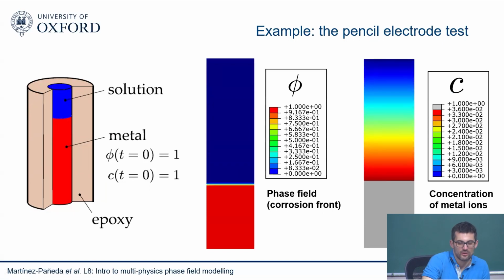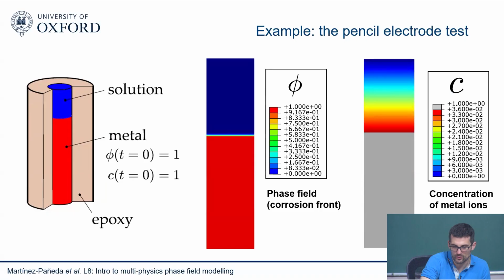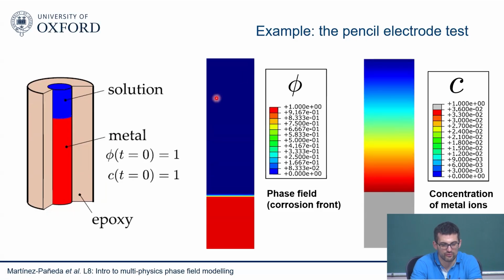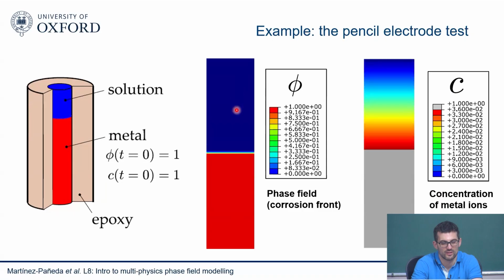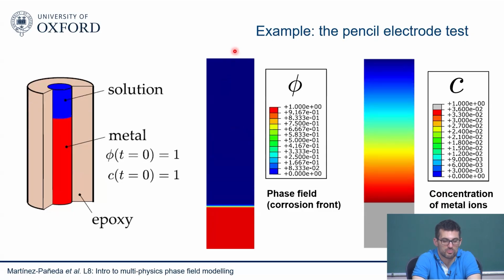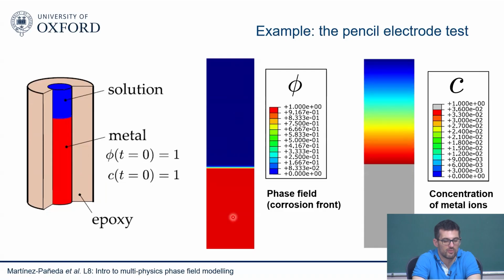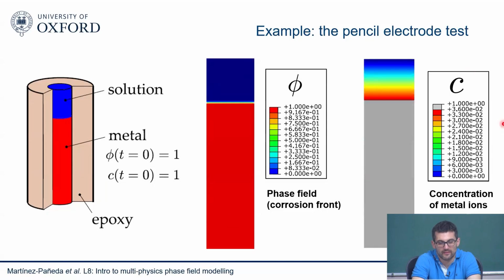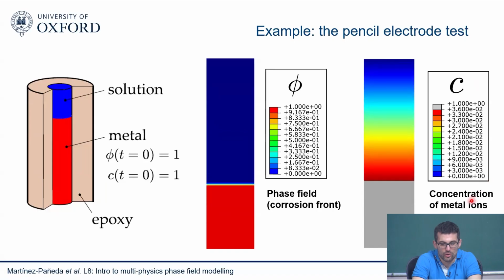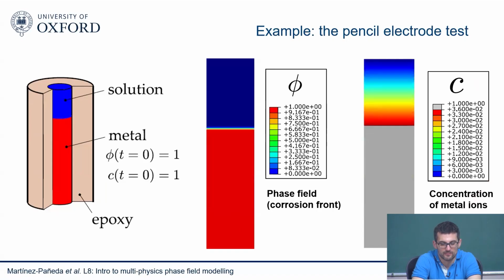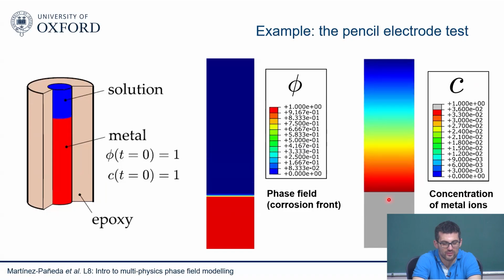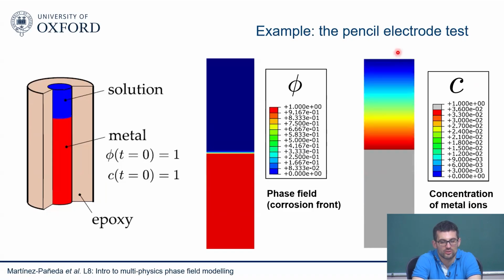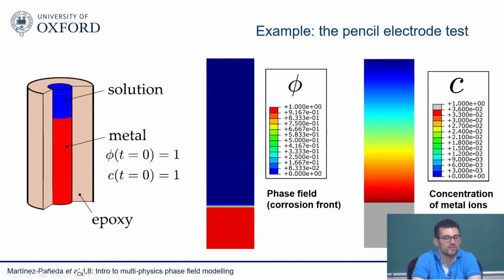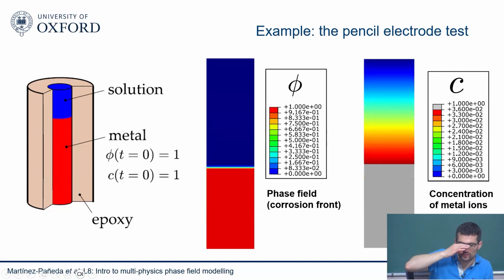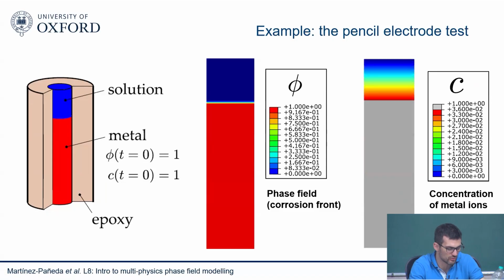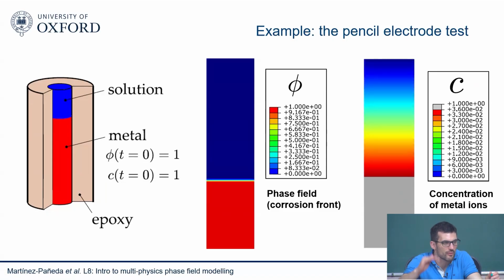This is the outcome of your finite element simulation. We solved this with COMSOL, Abaqus, and other tools. You see basically on the left the phase field, and how the phase field evolves in time. You see that it captures what you expect. As you corrode your sample, the corrosion front progresses. And this is the concentration of metal ions, which goes from the one in the metal to the saturated concentration at the interface, and then there's transport away into the electrolyte, and it's zero or close to zero very far away. So this is the behavior that you expect, and you can see that in finite elements, you're able to capture how the corrosion front evolves.